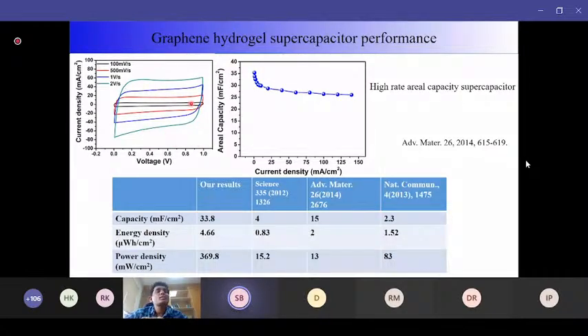So we have tested their energy storage performance with cyclic voltammetry. Cyclic voltammetry is just increasing the voltage from 0 to 1 volt at some 100 millivolts per second or 500 millivolts per second, 1 volt per second or 2 volts per second. When we do it, we can get the corresponding current. Ideally, this curve should be exactly rectangular in nature. Any deviation from the rectangular shape signifies that it is not a good capacitor. But here we can charge and discharge at even up to 2 volts per second. Within 1 second, I can charge it to 1 volt, but it's still showing a similar rectangular curve. It signifies that it is a very good capacitive material because of the presence of the pores, and electrolyte ions can move within these materials, and it is highly conducting.